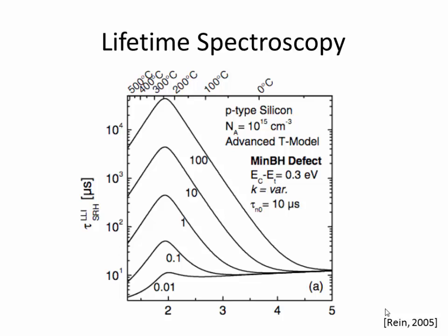And then if you know the trap depth, then from where the onset temperature is here, you can extract the asymmetry ratio, so the ratio between the capture cross sections of electrons and holes. So that gives you a fingerprint of the defect that's limiting the efficiency, which you can compare to literature and determine what specific crystallographic defect you're talking about and try to get rid of that in the material.